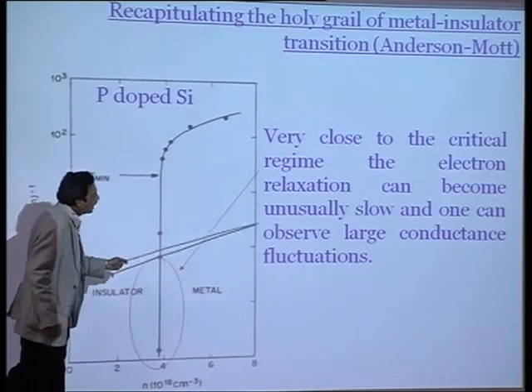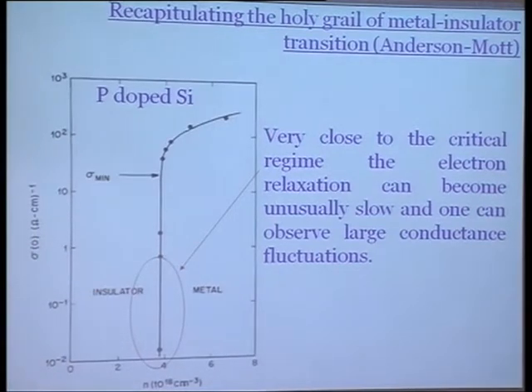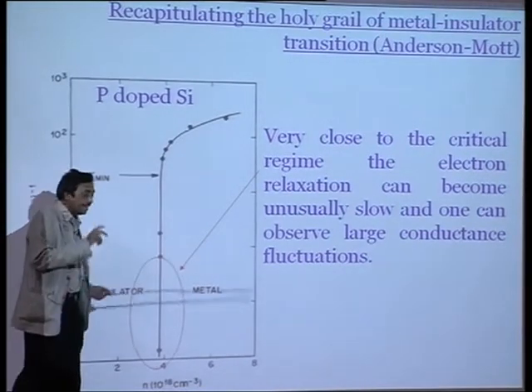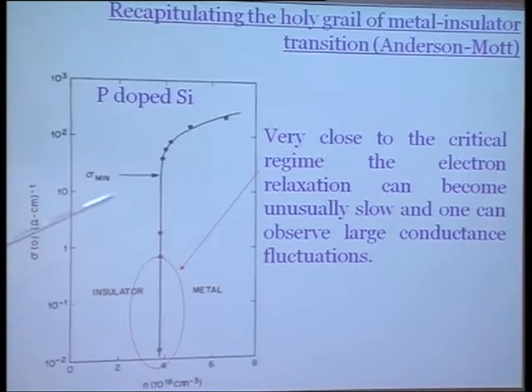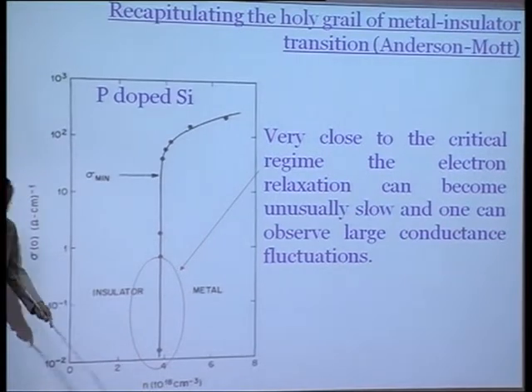The electron relaxation becomes unusually slow, and one can observe large conductance fluctuation. Let me tell you one thing: when I am talking of large conductance fluctuation over here, it is not universal conductance fluctuation. You see universal conductance fluctuation in the disordered metal type, and we saw that in Arindam Ghosh's thesis in 2001, when that paper came out. But when you come over here, it is not universal conductance fluctuation, it's a much larger fluctuation, and it is essentially coming from carrier fluctuation.